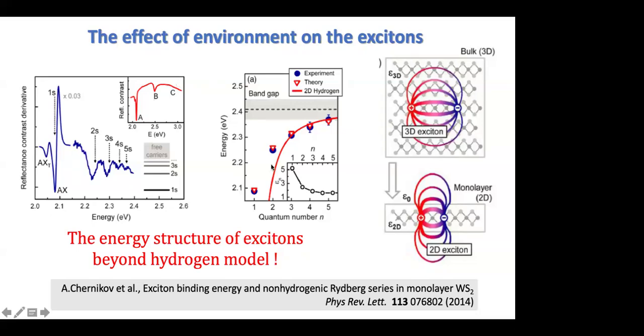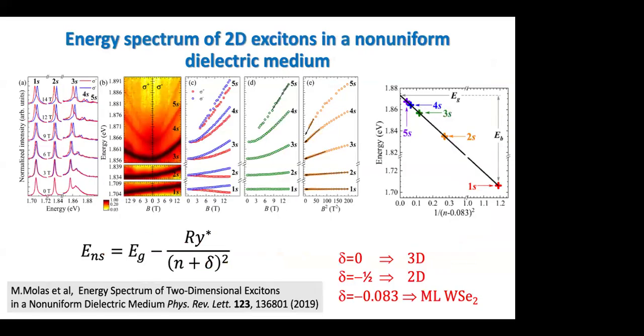So the result can be appreciated here in this slide. If you look at the experimental energy of excited states of an exciton in a monolayer, you will see that it goes very well outside the simple hydrogen model, which is used in this 3D system. Even the 2D hydrogen model, where you confine your carriers within the layer but you don't change the dielectric constants, doesn't fit.